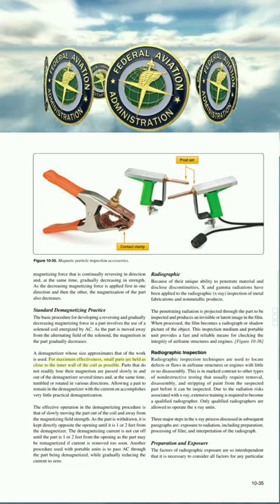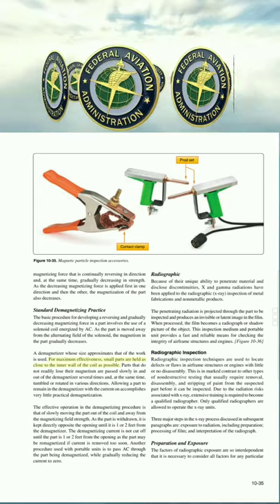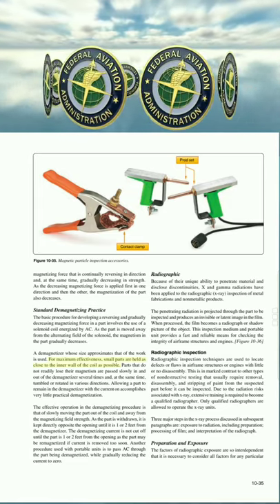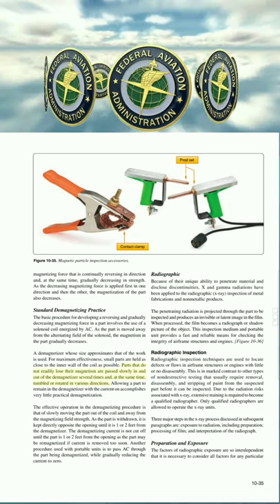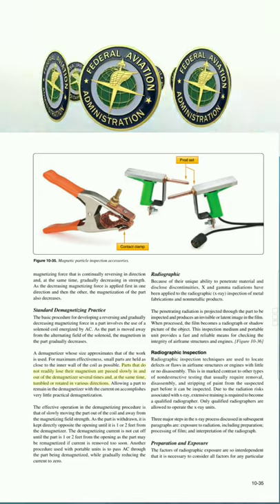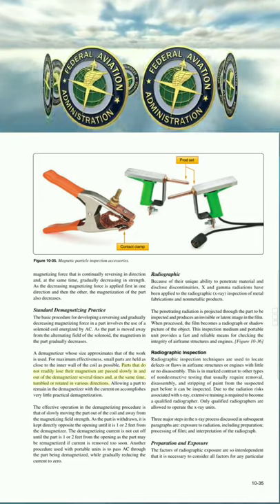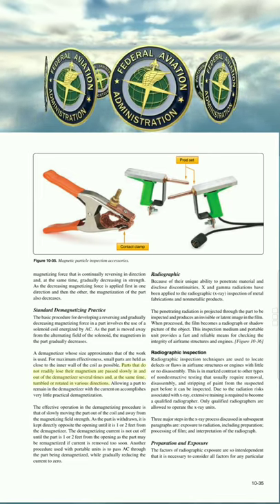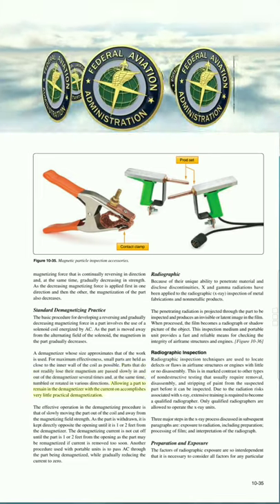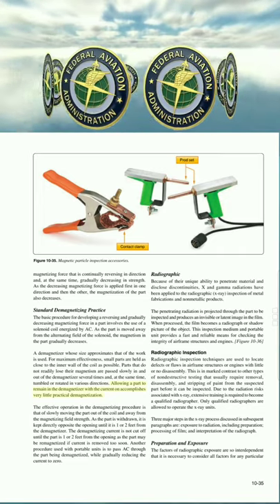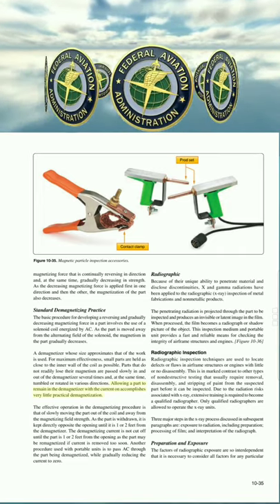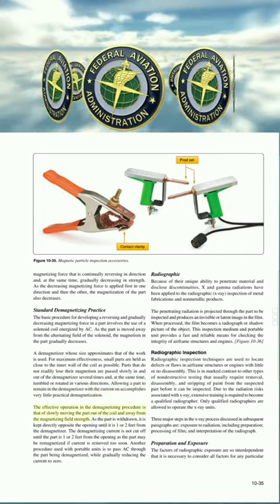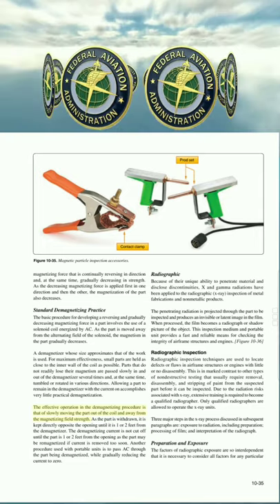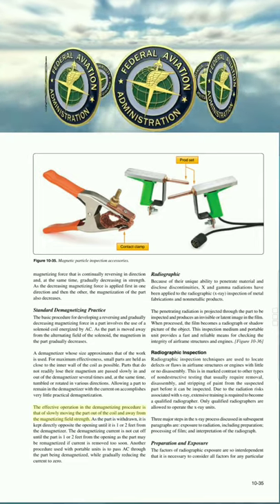For maximum effectiveness, small parts are held as close to the inner wall of the coil as possible. Parts that do not readily lose their magnetism are passed slowly in and out of the demagnetizer several times and, at the same time, tumbled or rotated in various directions. Allowing a part to remain in the demagnetizer with the current on accomplishes very little practical demagnetization. The effective operation in the demagnetizing procedure is that of slowly moving the part out of the coil and away from the magnetizing field strength.